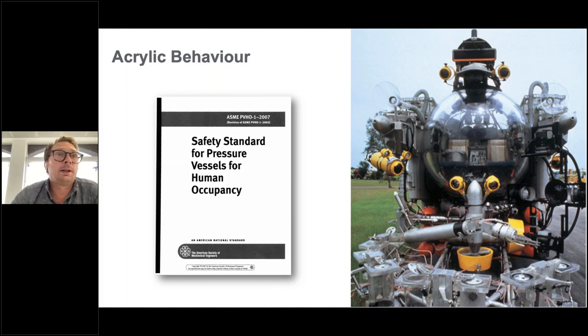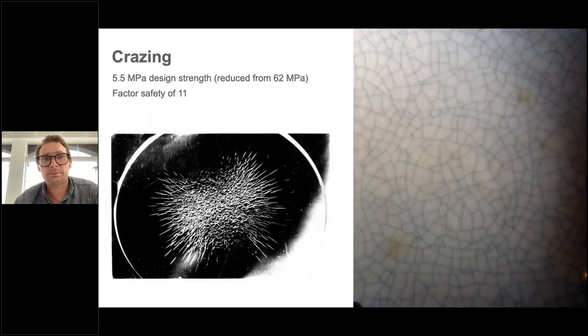But knowing now what Marcel's just told us, we've used a fairly significant conservative view. So it'd be interesting to see where we might get to with the material thickness, really understanding acrylic in much more detail. But principally, what we were designing to was long-term loads. And long-term loads really reduces our design strength, largely because at 5.5 MPa, below that, you start to get stress crazing.